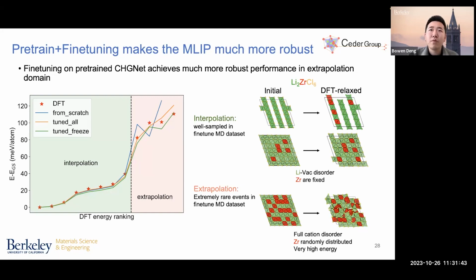where we use the lithium zirconium chloride AIMD trajectories to either fine-tune or train a CHGNet from scratch and observe the performance difference. We compare the performance of relaxation and energy evaluations on an ensemble of lithium zirconium chloride cells with different cation orderings. And what we have found is that in the interpolation domain, where only lithium vacancy disorder is considered, there is really negligible difference in your training strategy. You can see these three curves almost agree with each other. So we really don't care if we have enough data within this interpolation domain.